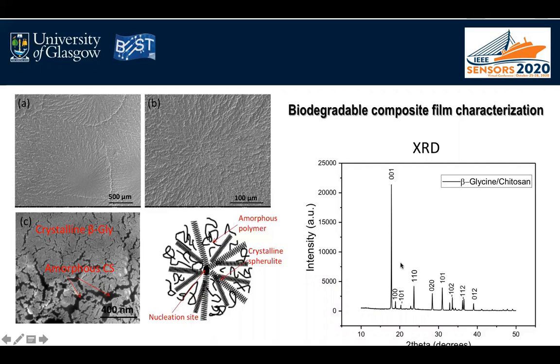And the XRD pattern of the composite confirmed the formation of beta phase of glycine crystals. And we noticed that crystals were very stable inside the chitosan matrix. We made the XRD after a few months. We haven't noticed any phase transformation in that. And we think this stability comes from embedding crystal inside the chitosan matrix. And also there is a possible electrostatic interaction between the polar group of glycine and functional group of chitosan.